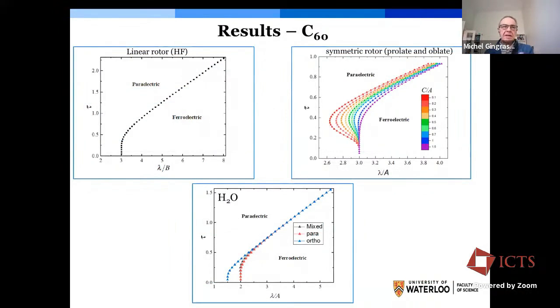Okay, so this is to illustrate as a cartoon what we find. For a linear rotor, we find that the phase diagram is quite simple. It corresponds to what I illustrated earlier. Lambda here is a scale parameter that is proportional to the square of the dipole moment and the lattice sum, the FCC dipolar lattice sum. B is again the rotational constant, and tau here is a reduced temperature, which is the physical temperature divided by the rotational constant. So same phase diagram as I illustrated earlier: a paraelectric phase, a ferroelectric phase at low temperature if the moment of inertia is sufficiently large in the semi-classical regime, and a quantum disordered phase where there is no longer a ferroelectric phase.